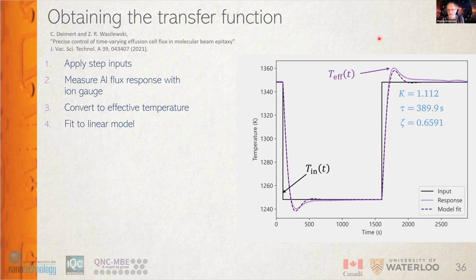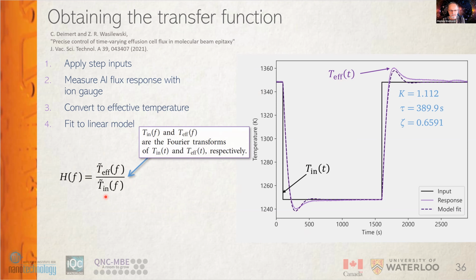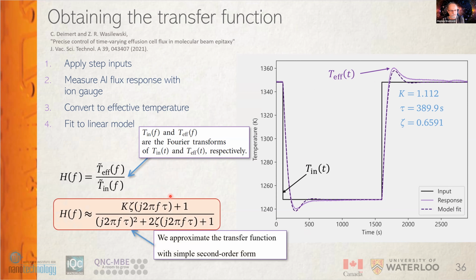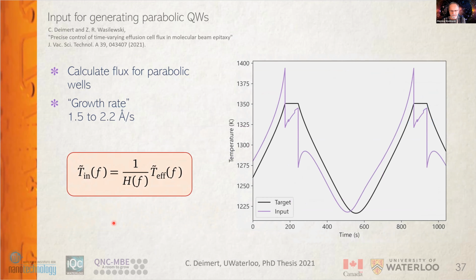And we want to learn from that, and you can construct the transfer function using the Fourier transform of those experimental data, and then use that to generate any profile you want. So after initially doing numerical calculations, we found that it's just as good, or even better, to approximate it with an analytical function, our transfer function. And the result is